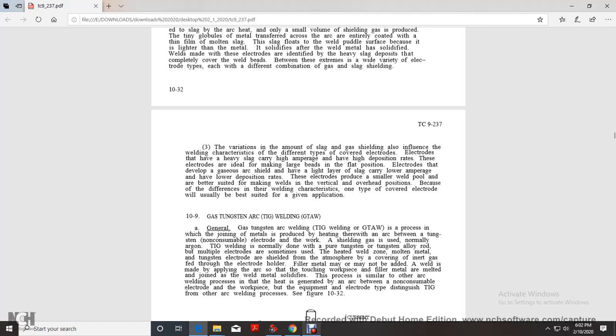The covered electrodes with heavy slag and high amperage have a high deposition rate, and these electrodes are ideal for making large beads in the flat position. Other electrodes develop a gaseous arc shield with a light layer of slag, carry low amperage, and have a low deposition rate. These electrodes produce a smaller weld pool and are better suited for making welds in the vertical and overhead positions because of the difference in welding characteristics. One type of covered electrode will usually be best suited for a given application.